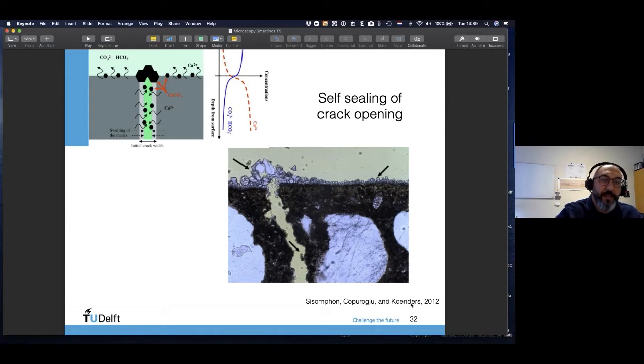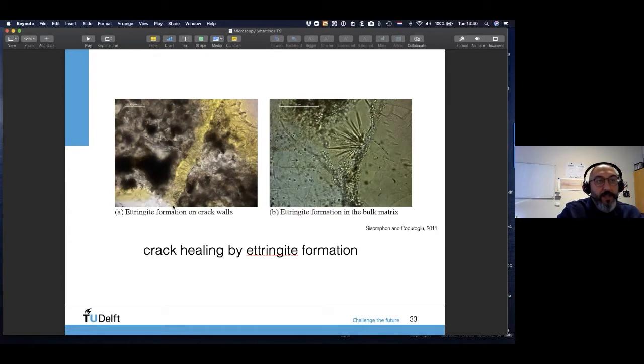Here you see one example from one of our studies, the self-sealing of a crack opening. So you observe here a crack opening, and we used a certain additive to promote self-healing. But what we observed actually was, instead of self-healing, we achieved self-sealing. Why? Possibly because higher carbon dioxide content at the surface triggered formation of calcium carbonate. So this is again a plane polarized light image showing all these deposited calcium carbonate crystals here.